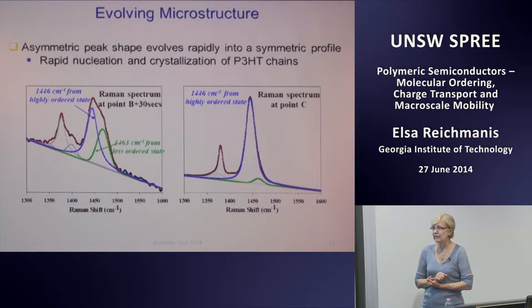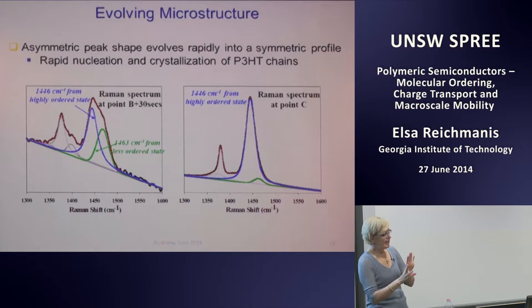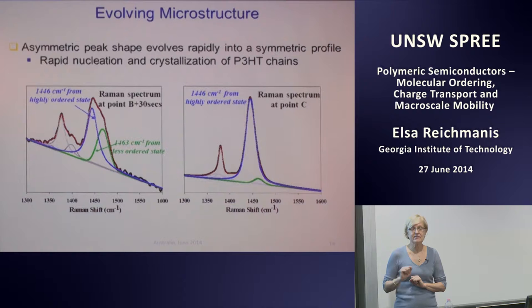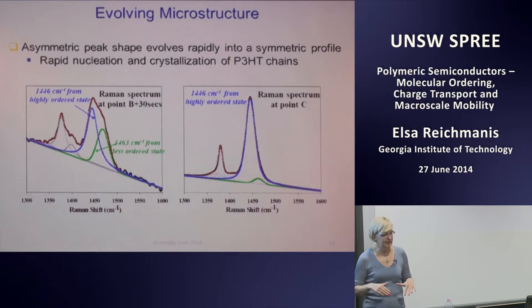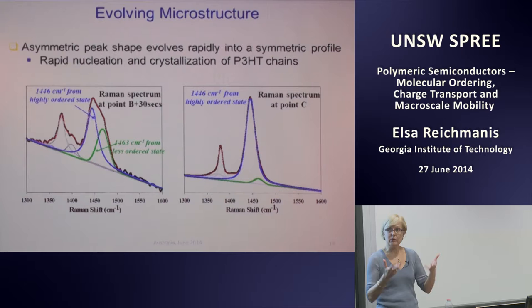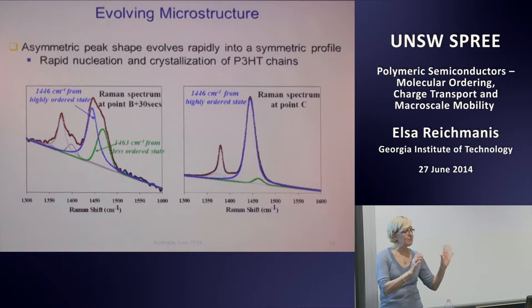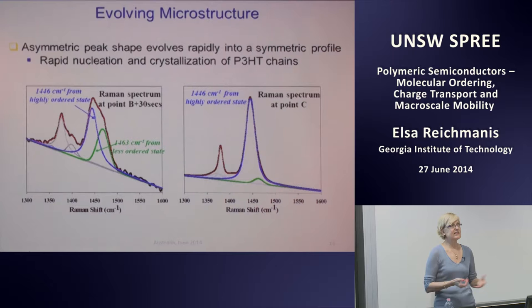But also in this region, we can look at the P3HT signals and deconvolute them to extract the ratio of highly ordered versus somewhat less ordered states of P3HT. We see that there is a change in that distribution in a very short time period, when most of the solvent has evaporated from the film, but there is still just a little bit of solvent remaining. So we're speculating that there's a period where we get a lyotropic liquid crystalline phase forming, but we also have rapid nucleation followed by crystallization of P3HT chains. In the final state, we have a polycrystalline network of poly-3-hexylthiophene.